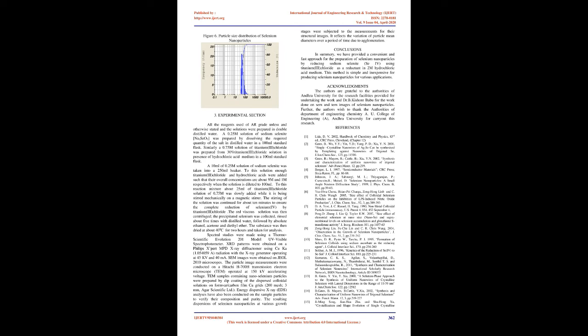10 ml of 0.25 M solution of sodium selenite was taken into a 250 ml beaker. To this solution, enough titanium(III) chloride and hydrochloric acid were added such that their overall concentrations are about 9 mM and 1 M respectively when the solution is diluted to 100 ml. To this reaction mixture, about 25 ml of titanium(III) chloride solution of 0.75 M was slowly added while it was being stirred mechanically on a magnetic stirrer. The stirring of the solution was continued for about 10 minutes to ensure the complete reduction of selenium(IV) by